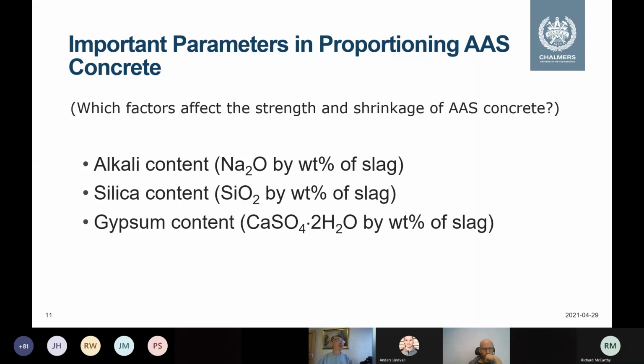And we also found another very important parameter: gypsum content. We use gypsum to decrease the shrinkage, and also to increase the calcium content. So there are double reasons for using gypsum.